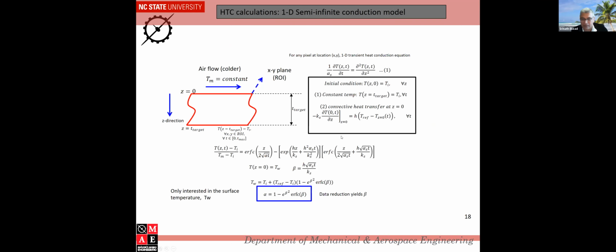How do we calculate the heat transfer coefficient from the images? What the images give me is the wall temperature response with respect to time. So we start the experiment when the cooler air enters the test rig, it starts changing color. So time 0, the air enters, and then we start seeing the color changes. We record the color changes, and we know the wall temperature from the color at every pixel on the test surface. And then we take each pixel as an independent pixel and apply what is called the 1D transient heat conduction equation, which is assuming that the heat transfer only occurs